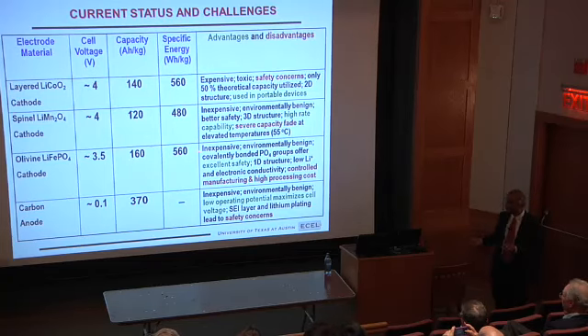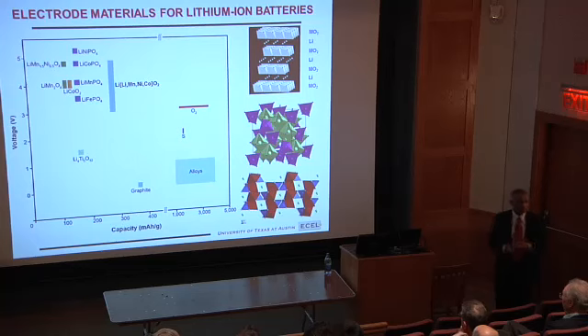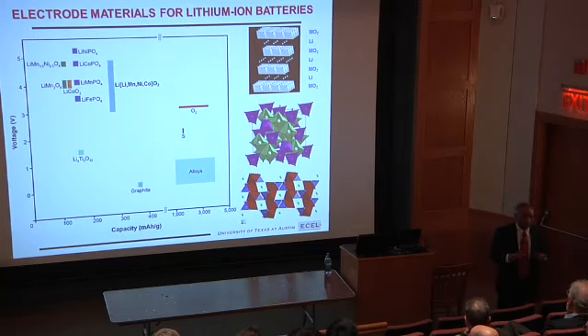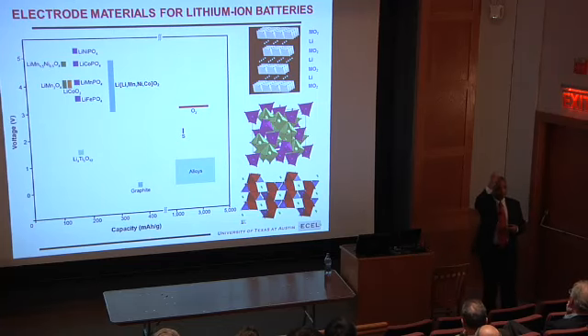safety. So there is a lot of work going on with silicon, for example. Silicon is not going to solve that problem. A lot of people, a lot of startups, are working on silicon because silicon has a charge storage capacity of 4,000 amp hour per kilogram as opposed to 372 amp hour per kilogram here, an order of magnitude higher. So everybody is marching on that, but silicon operating voltage is around 0.3, so that's not completely going to solve the problem. I have some other material, antimony, around 0.5 to 0.8, a little better.